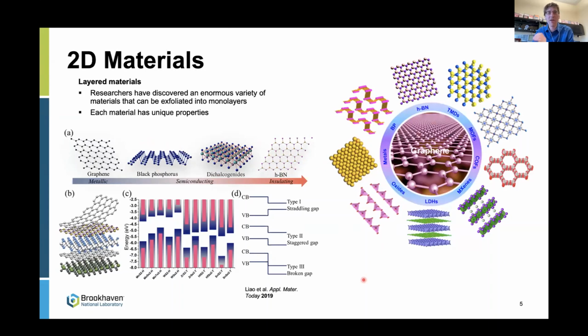The point is that after people discovered graphene, they discovered there's a whole bunch of materials that are similar to it in the sense that the bulk crystal is layered, right? There's one direction in which things are covalently bonded, and so it's really strong. And then in the other direction, the layers are just van der Waals interacting. So there's no covalent bond between them. There's just these van der Waals forces holding them together. And so the interactions in that direction are weak enough that you can split them apart in that direction. And with the Scotch tape trick, you can then get a monolayer of all of these materials: HBN, hexagonal boron nitride, black phosphorus, graphene, all of these different things.